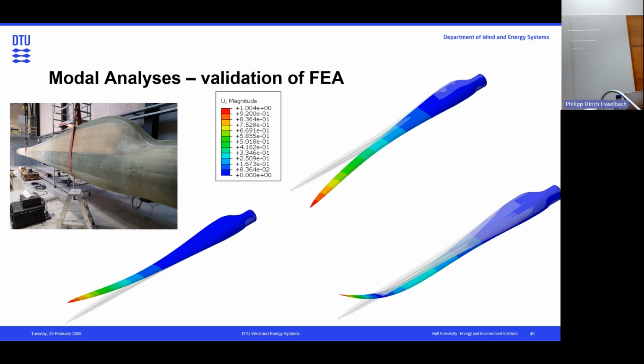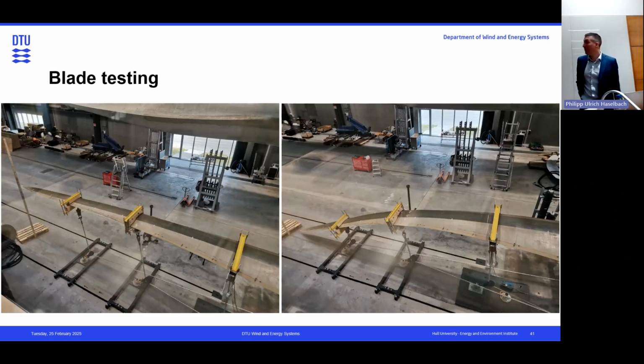And that's always the first step when we have a new prototype that we analyze. Then, of course, we also run testing. And usually for a wind turbine blade, you can say around about 1/3 of the length of the blade, you can also deflect it because the newer blades are quite flexible. So we do static testing. And I think this is not of so much interest any longer, but there we have showcased over the last decade that our numerical prediction tools get very close also when we simulate ultimate strength or ultimate failure of a wind turbine blade. So we can basically model exactly where and how the fracture occurs.